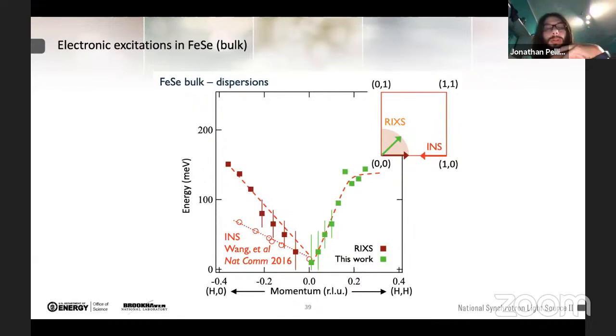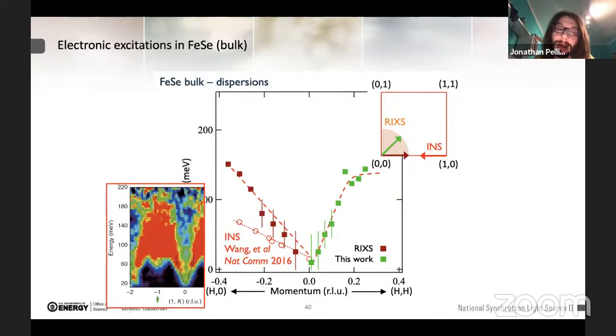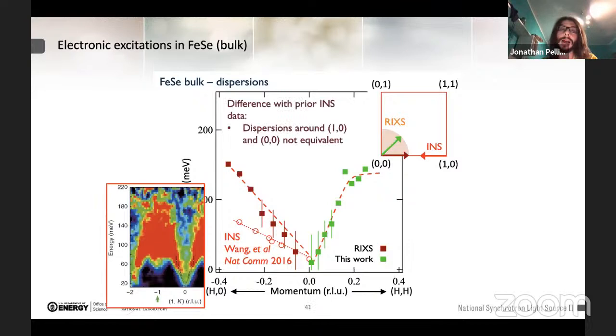And then we took from the literature inelastic neutron scattering data, and we observed that there is a slight discrepancy between our RIXS data and the neutron scattering data. And the reason for this is that inelastic neutron scattering data normally measures the spin excitation along the 1-0 direction, whereas RIXS looks in proximity of the gamma point. So in this case, where we have no long-range antiferromagnetic ordering, these two crystallographic directions are different, and this is the cause for the slightly different spin excitation dispersion.